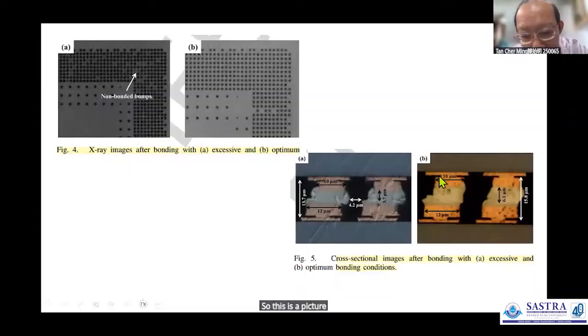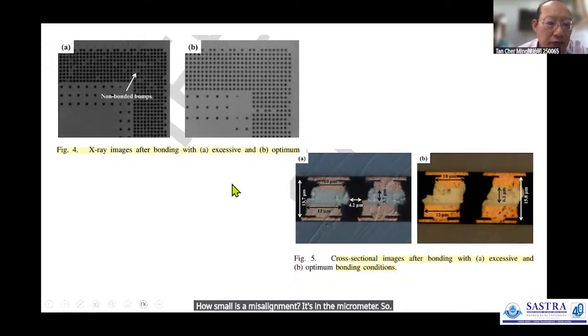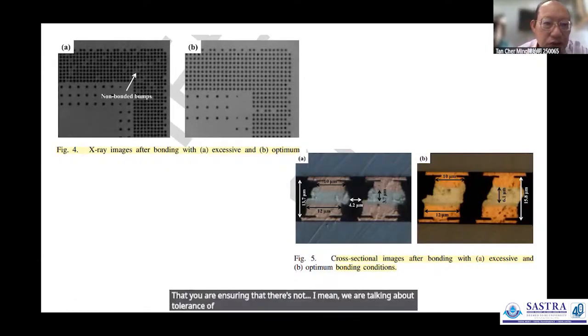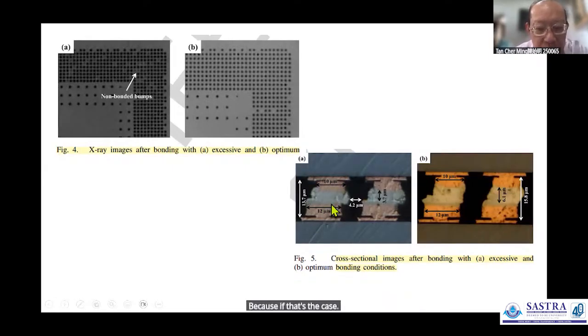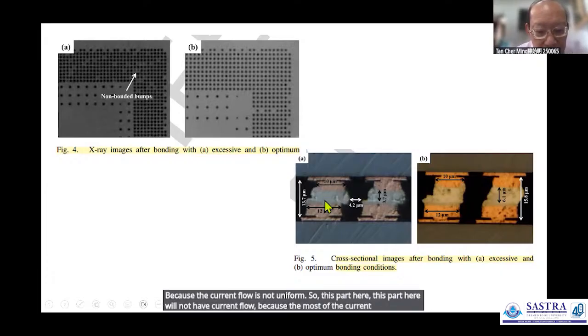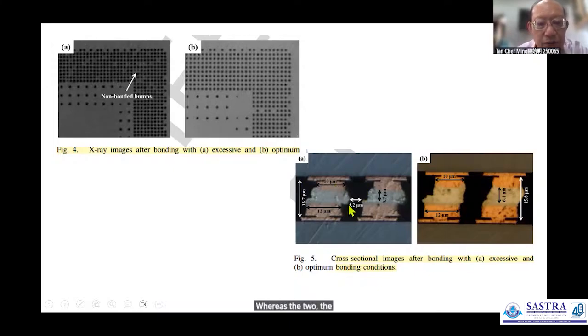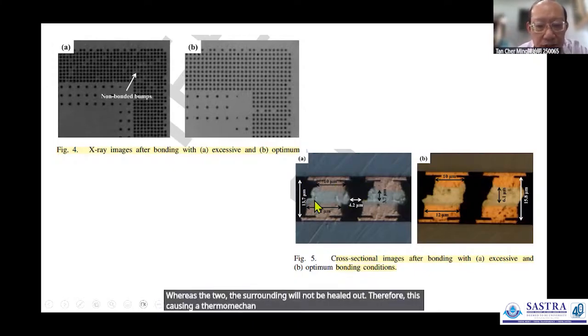So this is a picture of the misalignment of the bump, because this die is supposed to connect to the other die. And there is a misalignment. How small is the misalignment? It is in the micrometer range. So unless you have a very good tool, we are talking about micrometer tolerance. Because if that's the case, with prolonged operation, the stress will be non-uniform because the current flow is not uniform. So this part here will not have current flow because most of the current will flow in the middle. It will be heated up, whereas the surrounding will not be heated up. Therefore, this causes thermomechanical stress. In the end, the crack will form, and therefore you will see a crack line across it.